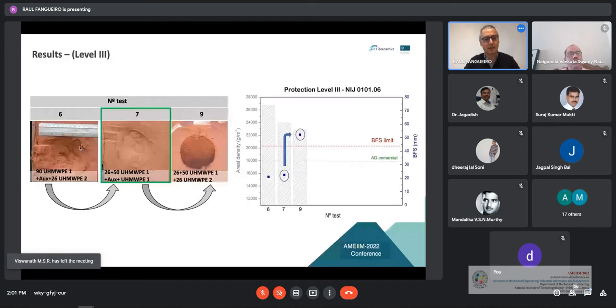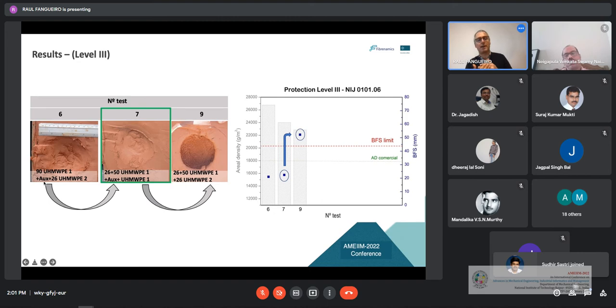sample 6, we are using auxetic material, so we are using 90 layers plus 26 layers of different materials, but then we insert one layer of auxetic material, and as you can see, we do not have a large deformation in terms of the thickness of the material. And if we remove this auxetic layer, we have a deformation like this. So the backface signature is much higher in terms of the deformation of the material.